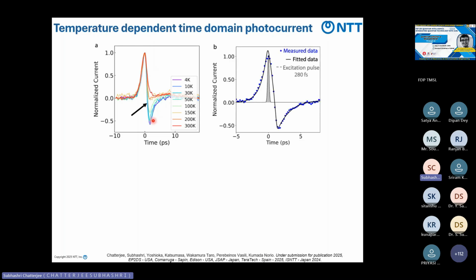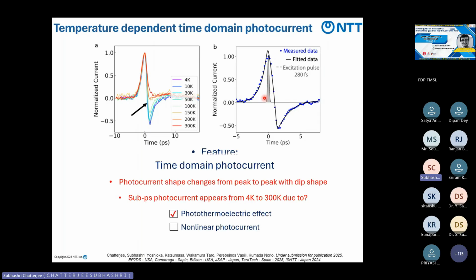To understand that, we compared it with our pulse laser duration, around 280 femtoseconds, and this response is much slower than the pulse laser. So we confirm this is because of the photothermoelectric effect, not the nonlinear effect, because nonlinear response should occur within 1 picosecond or at the femtosecond level.